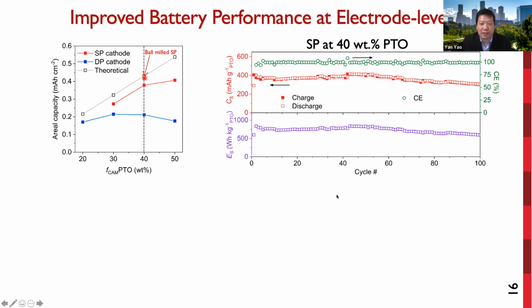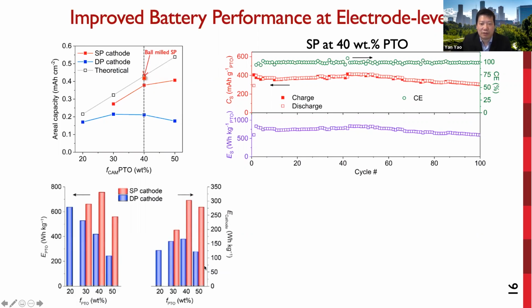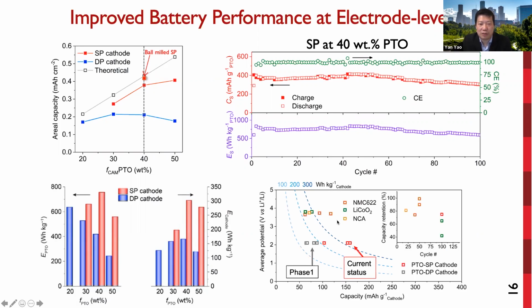We also compare the specific energy considering the total cathode mass in this figure. So the value can reach 300 watt-hour per kg, which is on par with inorganic cathodes, such as lithium cobalt oxide, which has a lower capacity but a higher voltage. But we show better cycling is possible without any coating applied. So this work shows our effort in using earth-abundant materials that can potentially lower the cost and reduce the reliance on any metals. There are also still many challenges to overcome, such as the low density of organics, or reducing the electrolyte thickness to less than 50 micrometer to improve the volumetric energy density and rate performance. So that's the first example.